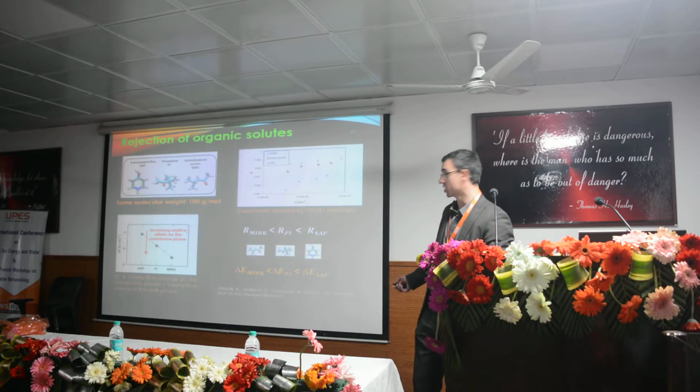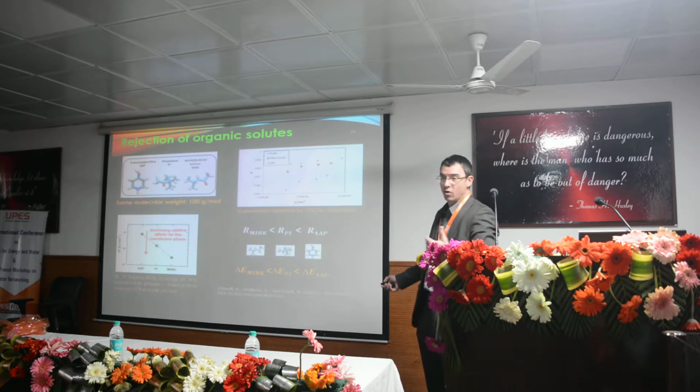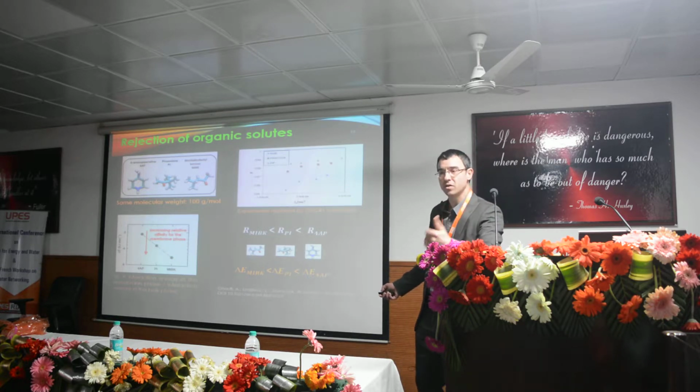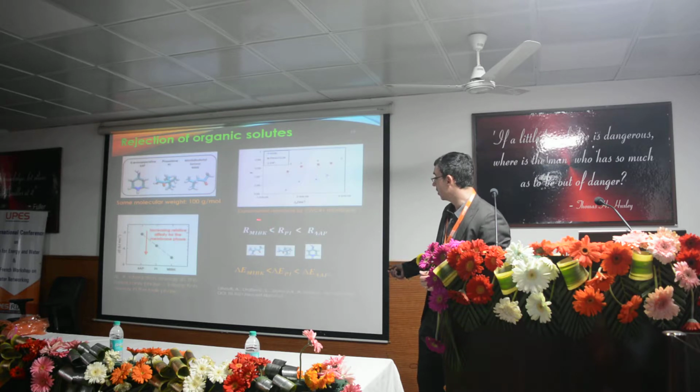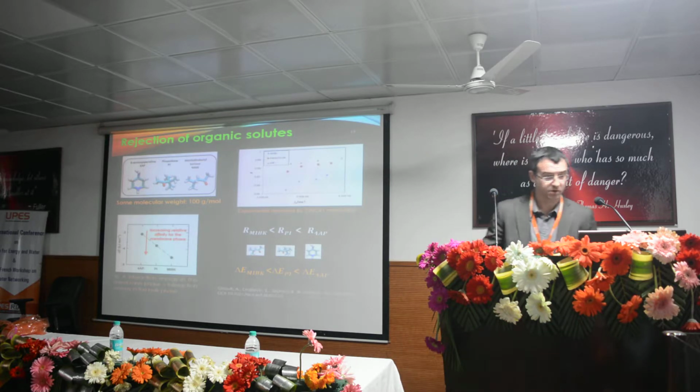then you observe a clear correlation between the affinity for the membrane phase and the experimental rejection. As you can see here, for the methyl isobutyl ketone, we have a rather strong attractive interaction, which means a relatively high affinity toward the membrane phase, and this is related to a lower rejection rate. On the other hand, the affinity for the 4-aminopiperidine towards the polyamide membrane is rather low, and this corresponds experimentally to a rather high rejection rate. So there is a clear correlation between simulation and experiments.